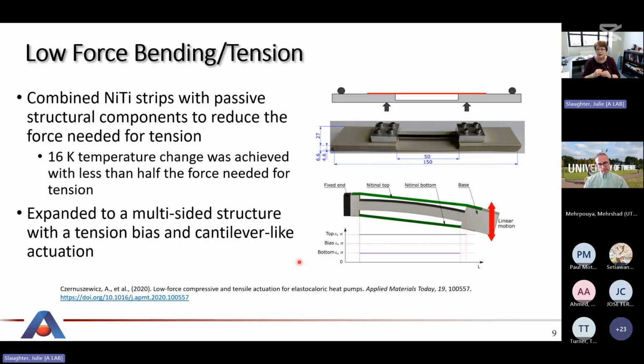So now we're going to get into a little more details about some of the work we've done at Ames Lab. So we've really focused on this, how do we reduce the forces needed and match the elastocaloric element with the actuators that are available. So one of the first things we did is look at, how can we reduce the force? Because with actuators, typically, we can produce more displacement than force in a lot of this actuation material. So what we've done is we've taken this active nickel titanium element and combined it with a passive structure so that when we bend this, and bending takes a lot less force, we actually get tension on this upper element in this 4-point bend configuration, and we used half the force to do that.